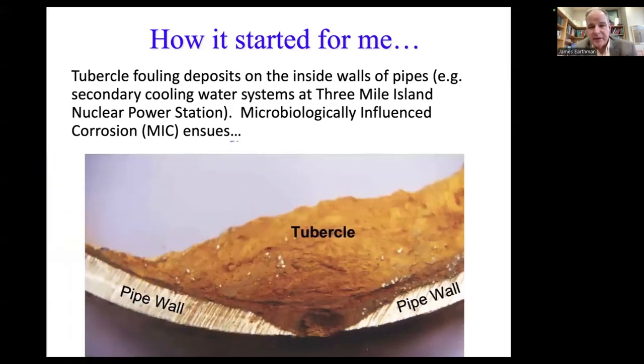And this is the problem that they create eventually, is that these tubercles get colonized by bacteria that can induce corrosion. The upper parts of the tubercle are typically colonized by aerobic bacteria. They consume the oxygen coming in, diffusing into the tubercle. And then at the bottom, there's typically anaerobic bacteria like sulfate-reducing bacteria that can thrive down there because there's very little oxygen as a result. And the sulfate-reducing bacteria create iron sulfide. And the iron for the iron sulfide comes from the pipe wall. And so as you can see, you tend to get this localized corrosion, and eventually the bacteria will eat through the pipe wall, and then you have a leak and you have to shut down the system.